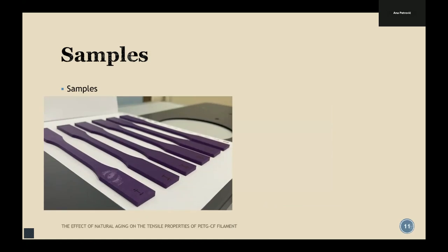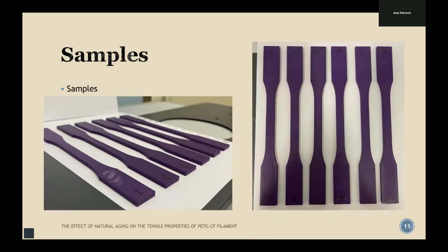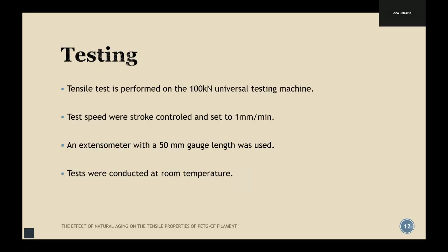Okay, so the looks of the new samples are presented here, and after 300 days, these are the 6 aged samples. We can see that the dimensions and the shape and everything is the same, but a total of 12 samples are tested. Testing was performed on a universal testing machine, which we use mostly for metallic materials, at 100 kilonewtons maximum force. Because of the big maximum force, and because of the standard, we performed testing by stroke control, set to 1 millimeter per minute, because we want to get results as precise as we can in terms of force and deformations. An extensometer with 50 millimeter gauge length was used, and tests were conducted at room temperature.